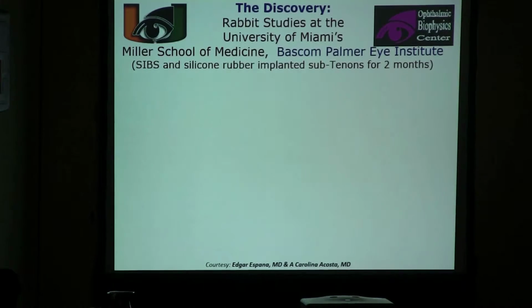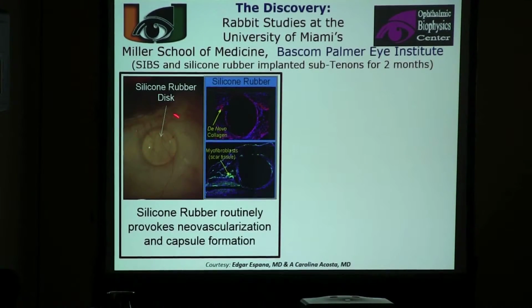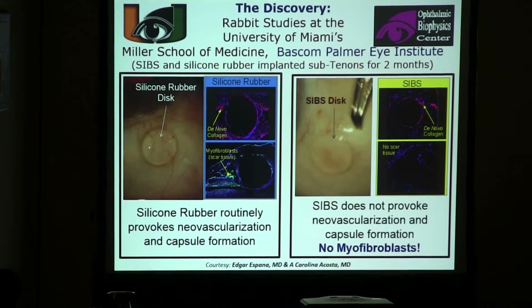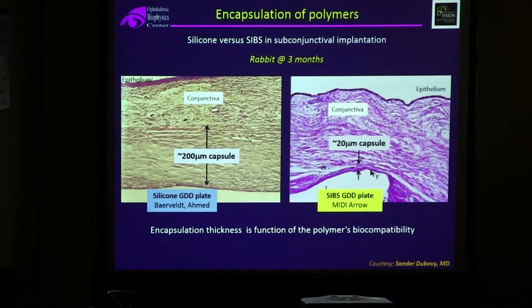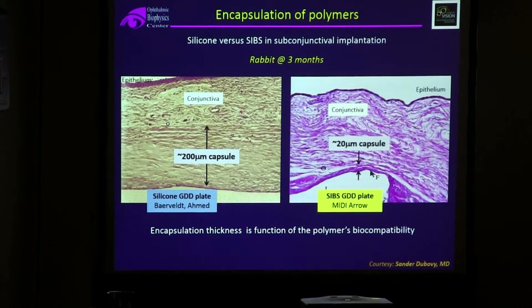They also put it subconjunctival, but they had controls of silicone rubber discs. This is polydimethyl siloxane that are used in the Ahmed and Baerveldt valves. And in these discs, you get neovascularization. You get myofibroblasts that cause scar tissue formation, and you get a lot of de novo collagen. So you form capsules around silicone rubber. However, with SIBS, they found no neovascularization, no myofibroblast, and no capsules. In fact, when they dissected the eye, these polymers just fell out. They were not where they left them. And if you look at histology, you'll see around silicone rubber, you have 200 micron capsules, whereas around SIBS, it's a very loosely bound layer, around 20 microns of just cells.